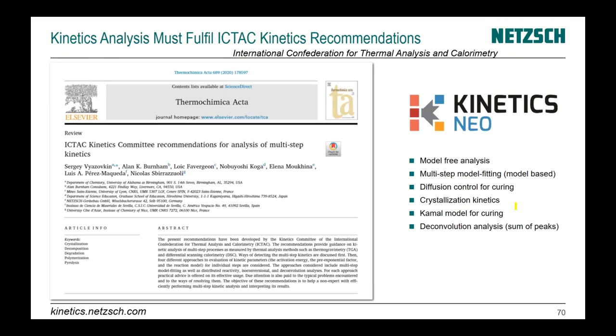Thank you Elena for this great presentation. I would like to directly start with the first question: could you tell me how one can check if model-free kinetics is applicable for my process? So, again, firstly you must check if all your data fulfill all the requirements which are listed here — the measurement must be complete, total effect must be the same, changing of mechanism should happen at the same value of conversion. The second and easiest way is just to see if the fit is okay or not, because sometimes in the literature only activation energy is found and if the fit is not present we cannot say if it is valid.